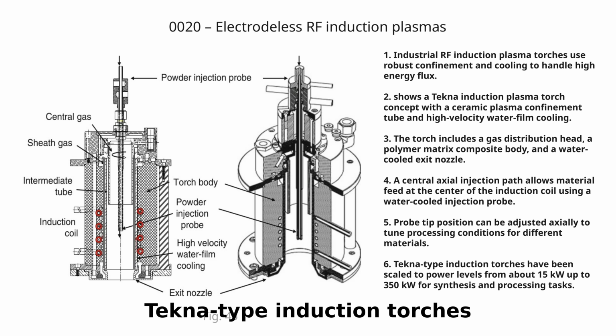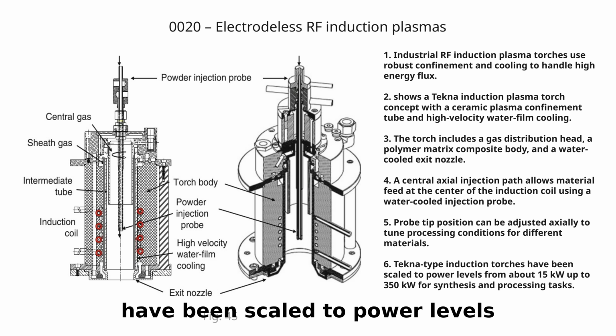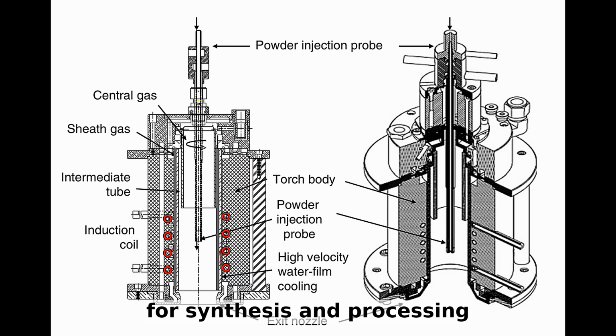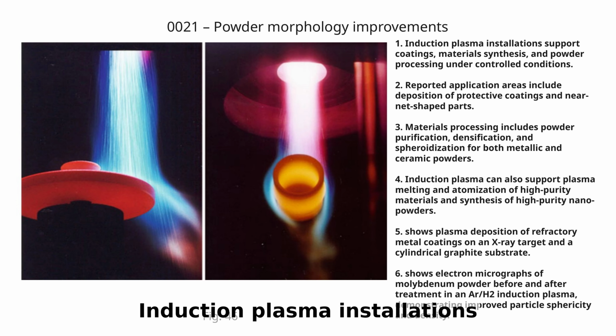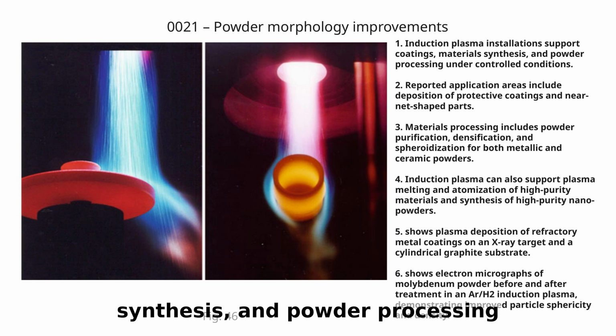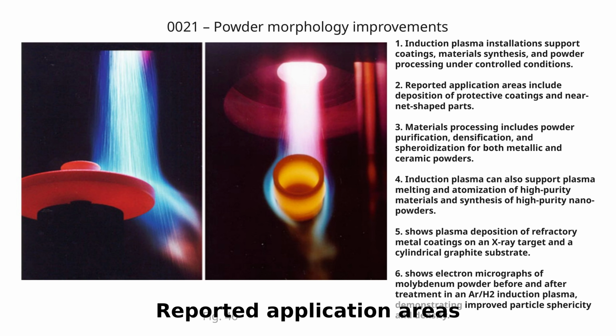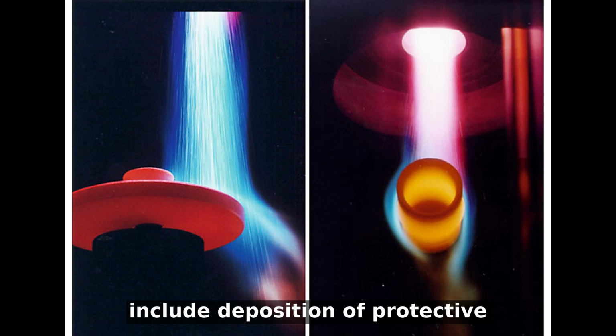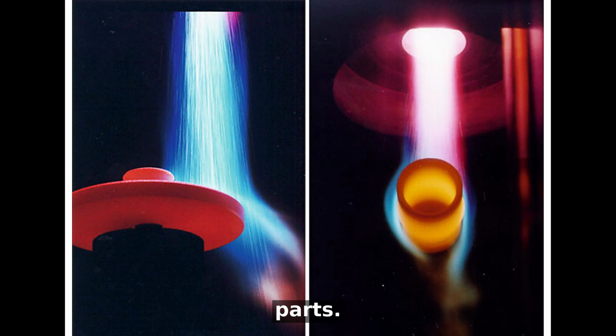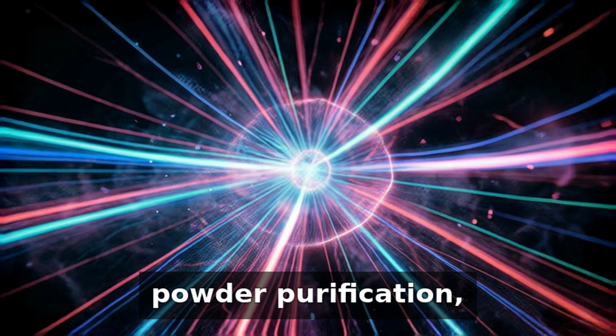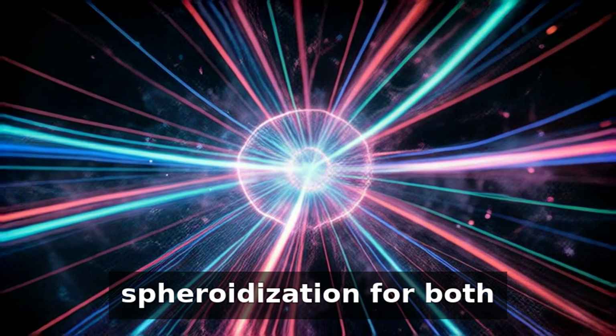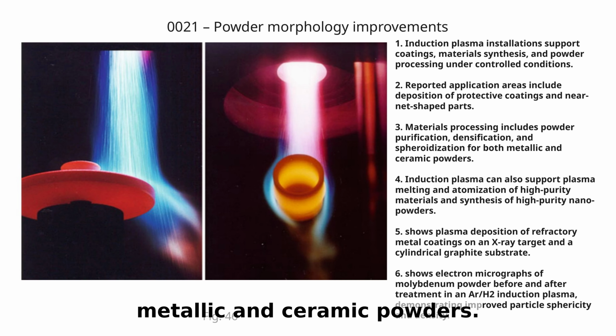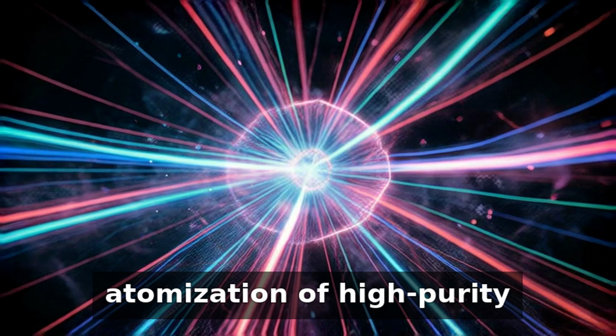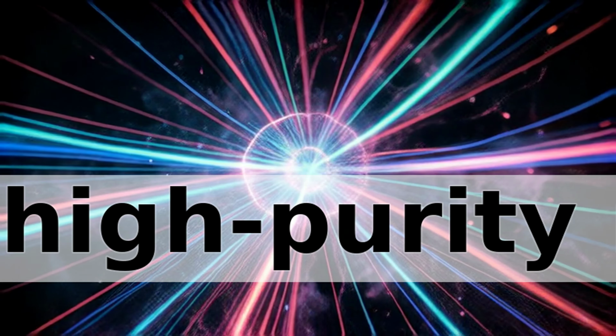Tekna induction torches have been scaled to power levels from about 15 kilowatts up to 350 kilowatts for synthesis and processing tasks. Induction plasma installations support coatings, material synthesis, and powder processing under controlled conditions. Reported application areas include deposition of protective coatings and near-net-shaped parts. Materials processing includes powder purification, densification, and spheroidization for both metallic and ceramic powders. Induction plasma can also support plasma melting and atomization of high-purity materials and synthesis of high-purity nanopowders.